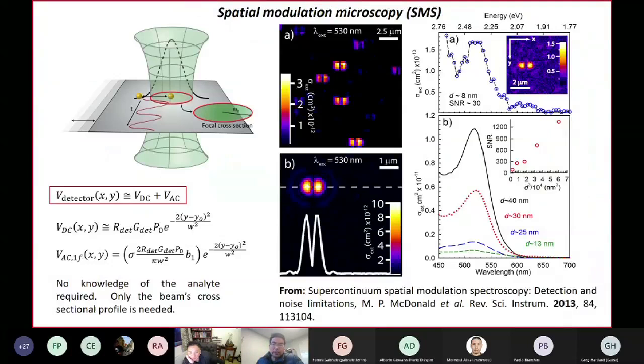In addition to photothermal heterodyne imaging, there are alternate techniques that we have also been pursuing, and that includes spatial modulation spectroscopy or microscopy. The general idea is you got your particle at the center of a tightly focused laser beam, and you're going to modulate the position of the sample in and out of that tightly focused laser beam. Because we're doing this in a periodic fashion, we can use lock-in detection. This AC term has a pre-factor proportional to the extinction cross-section of the particle, and this value is frequency-dependent. If you have a tunable laser, you're able to map out the absorption spectrum or extinction spectrum of your particle or object of interest.